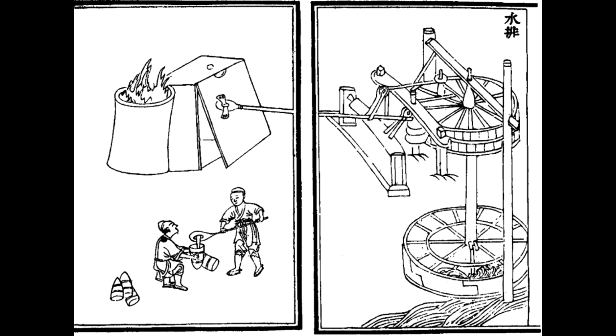More slowly cooled cast iron with high silicon content can come as gray cast iron, which has less cementite but has instead pockets of graphite, little pockets of pure crystalline carbon which couldn't be absorbed into the iron, which have very little strength and essentially function as cracks within the iron, reducing the overall toughness considerably. Craddock notes that early Chinese cast iron tends to be gray cast iron, but, curiously, with somewhat lower silicon contents than we'd expect for gray cast iron. So, for almost any tool or weapon use, our cast iron is functionally worthless, too brittle to sustain meaningful stress.